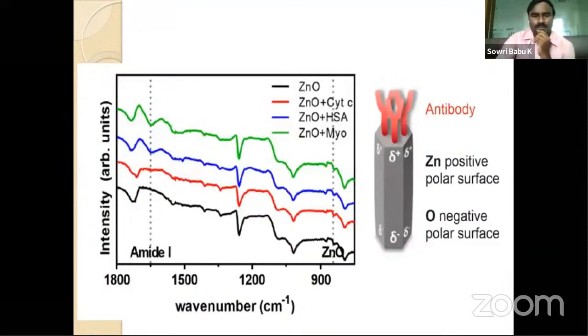Our work is different from other work, because what we have done here is we have directly immobilized the antibodies on the surface of the zinc oxide nanorods by using its polar surface. If you see the picture here, the top of the zinc oxide nanorod is positive and the bottom of the zinc oxide nanorod is negative. So this property we have used to directly immobilize the antibodies on the surface of the zinc oxide.